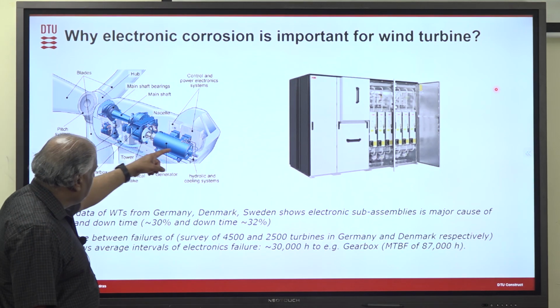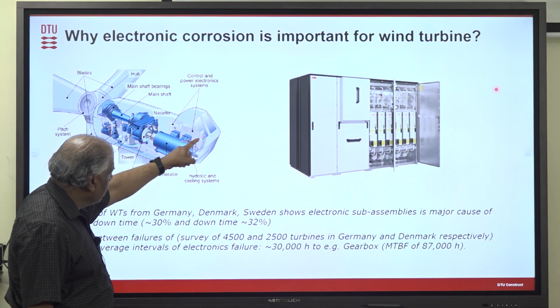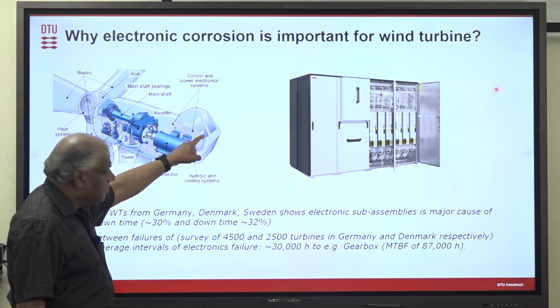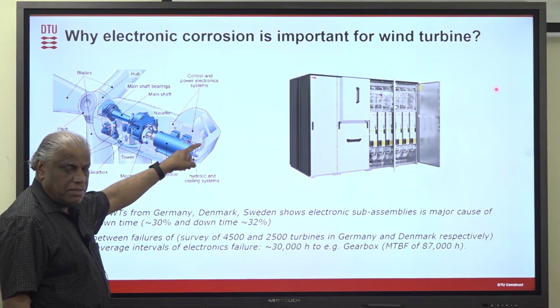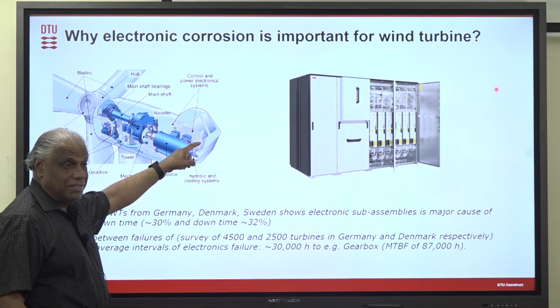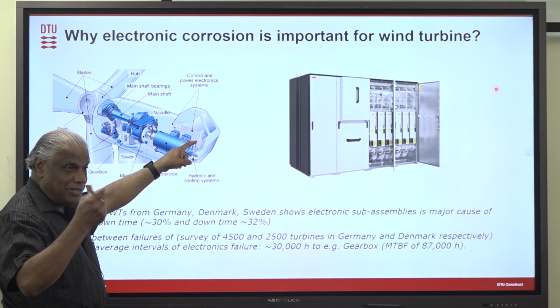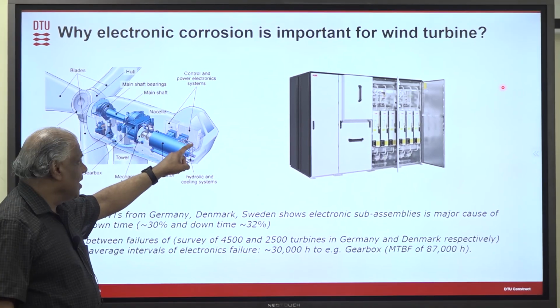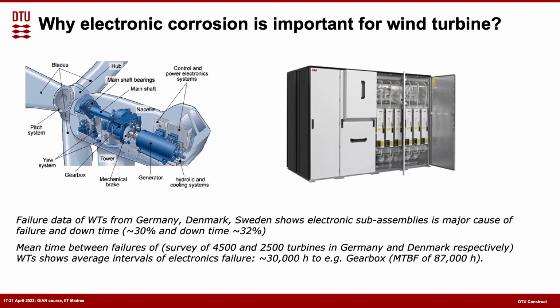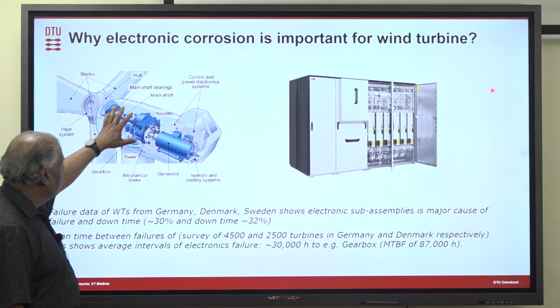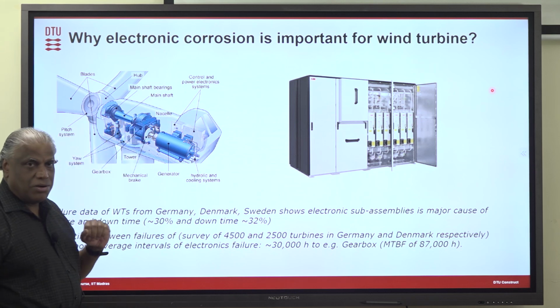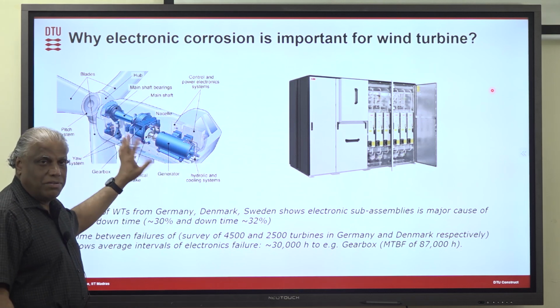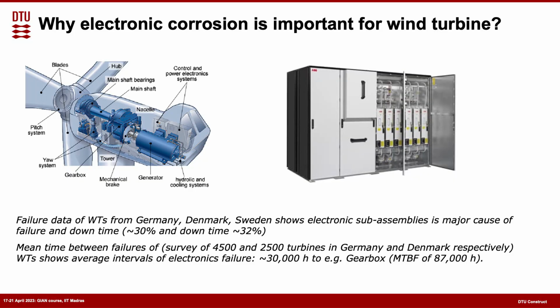So mainly the copper parts which I am talking about are from the generator to these electric connections here, and many of these parts are made of copper, because what you are talking about is very, very high current. So you need to have a real copper bar to take that current. A small wire is not enough to connect between these two. So that's more or less the structure. That's why I tell you, if the wind turbine is working, this gearbox will generate a lot of heat, and that way you have a lot of low humidity inside. Most of the time when the wind turbine is not working, that's the time you have the problem.